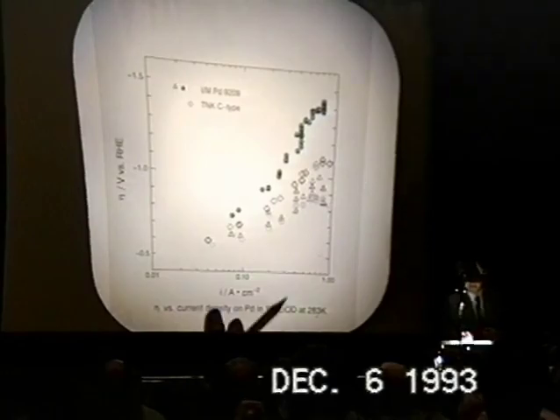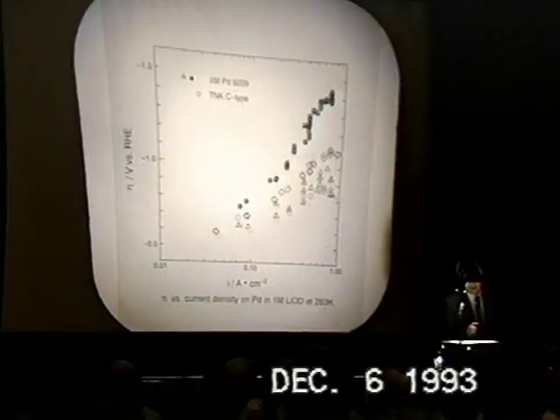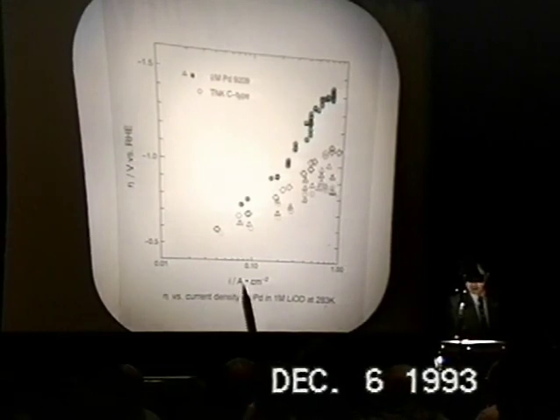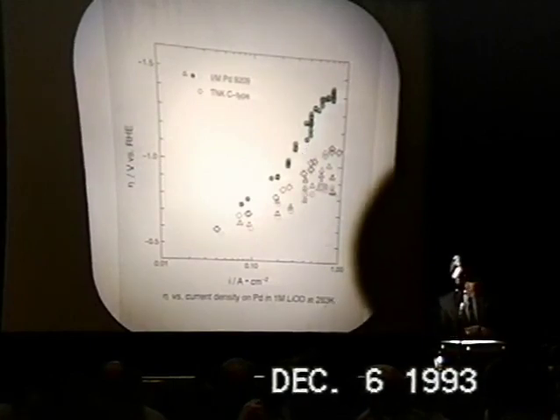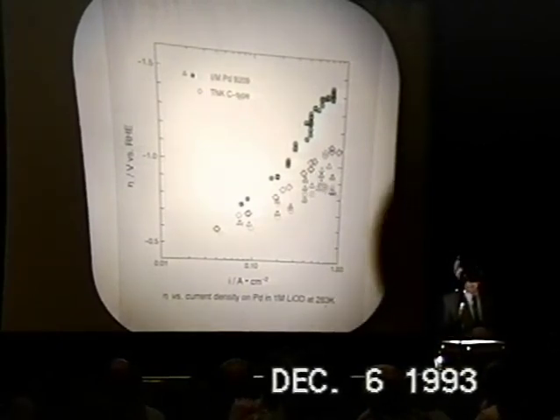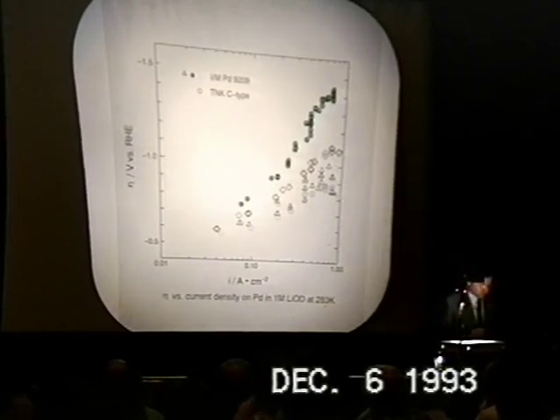And I'm showing by this figure the relation between cathode overvoltage and current density, which is usually called the Tafel line by electrochemists. So the green one, which we presented at our conference, shows very high hydrogen overvoltage compared to various other hydrogen cathodes. We still do not understand why this particular hydrogen cathode gave a much higher cathode overvoltage than others.